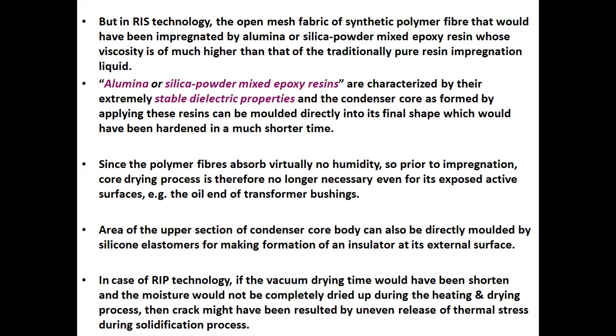Alumina or silica powder mixed epoxy resins are characterized by their extremely stable dielectric properties, and the condenser core formed by applying these resins can be molded directly into its final shape, which is hardened in a much shorter time. This is the advantage of using silica powder or alumina mixed epoxy resins. Since the polymer fibers absorb virtually no humidity, the drying process prior to impregnation is no longer necessary, even for the exposed active surfaces, as for example, the oil end of transformer bushings.